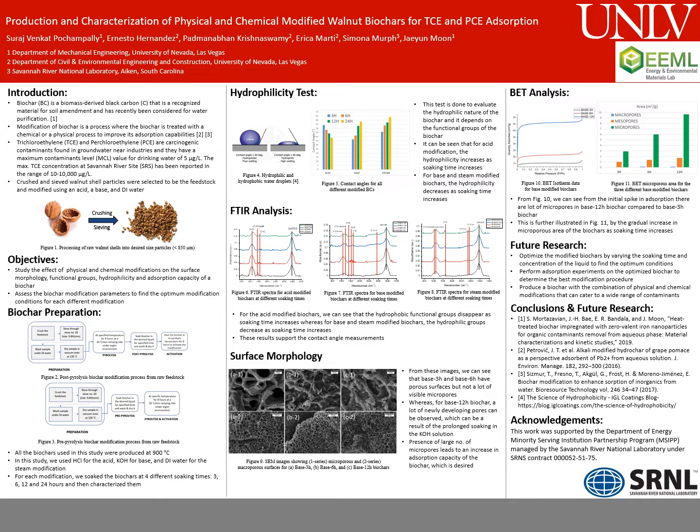Then we gathered images using scanning electron microscopy of the biochar surface and the pore structure. Here, the SEM images for base modified biochars are shown in figure 9, and the 3-hour, 6-hour, and 12-hour biochar images can be seen. We identified that as the soaking time increased from 3 to 12, there were a lot of small-sized pores that were developed in the biochar. It can be seen here in figure C1.